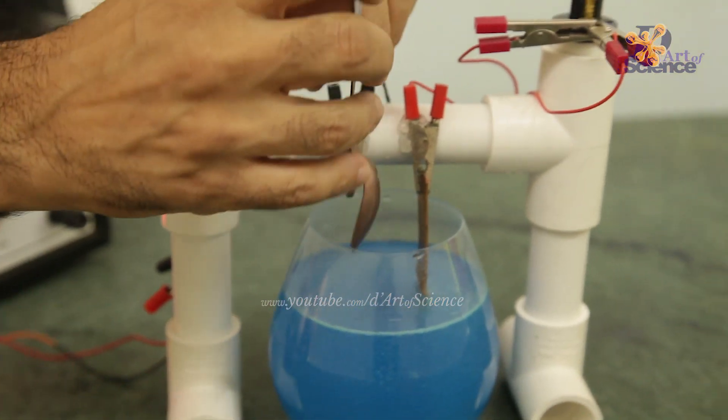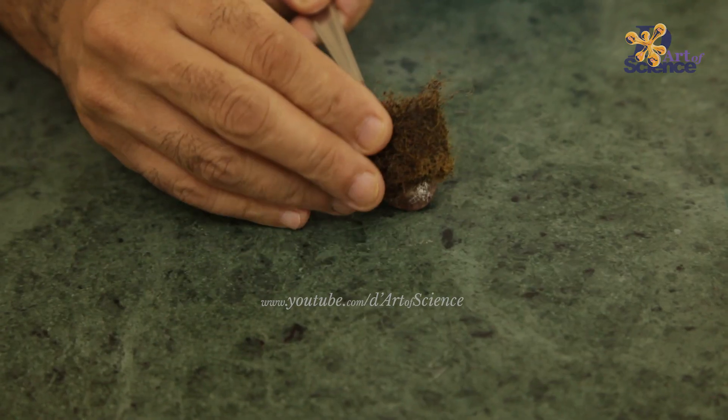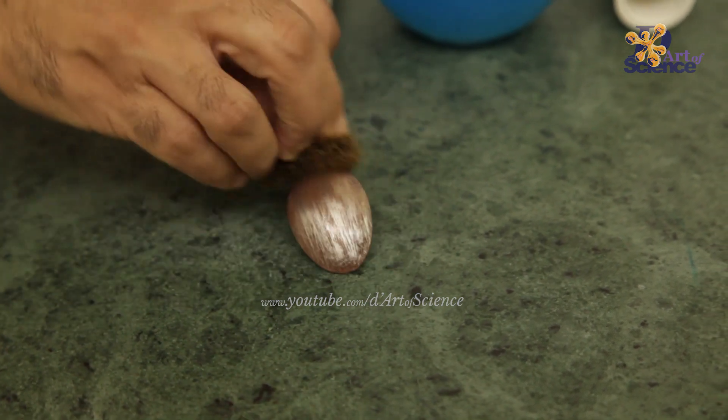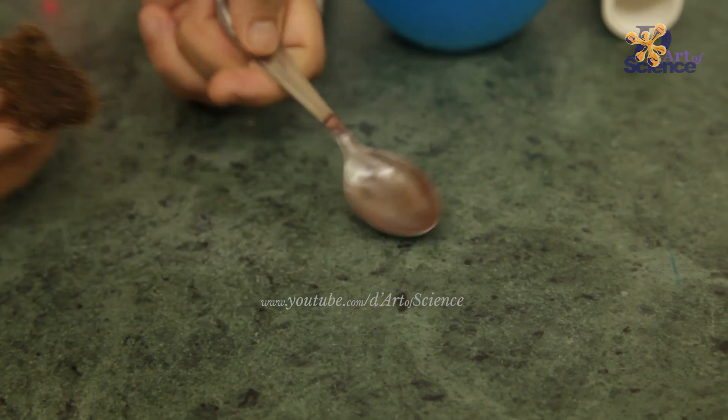Some coating does seem to be left behind, so let us try a few more layers. But once again when I wiped it, especially with the dish washing scrub, the full coating started coming off. Stainless steel is a failure.